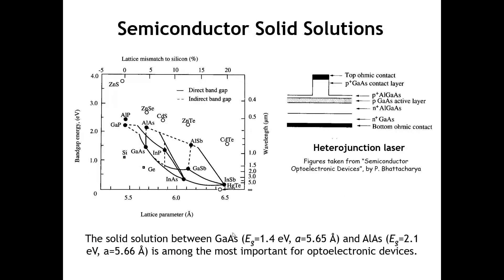This is quite important in the field of semiconductor devices. Oftentimes in this field you have epitaxial thin films — you have a crystal, and then you grow another very thin crystal on top of the base crystal, matching bonds at the surface. So the lattice constants of the different layers in this epitaxial device matter; we generally want to make the lattice constants as similar as possible. But at the same time, we want to vary the band gaps of different layers to get a certain function — for example, in a heterojunction laser. A really useful solid solution for these devices is between gallium arsenide and aluminum arsenide, because their lattice parameters are quite similar, so you can still grow these epitaxial films while tuning the band gap from over 2 eV for aluminum arsenide down to about 1.4 eV for gallium arsenide.